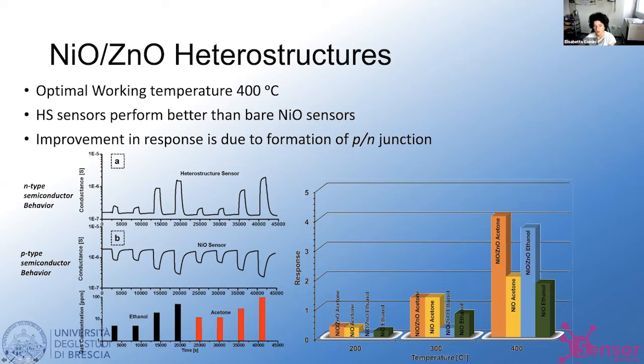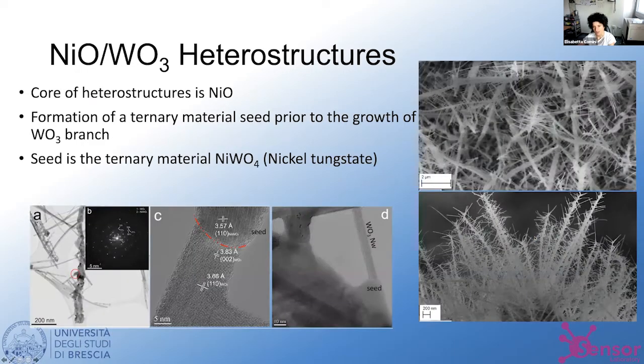And if we compare the response over the temperature to acetone and ethanol for the nickel oxide and for the heterostructure, we can see that we have an enhancement in the response toward these volatile organic compounds in the case of the heterostructure itself. Of course, we can try the combination of many and many materials, and this is what we are doing. And we have tried to grow tungsten oxide on top of nickel oxide.